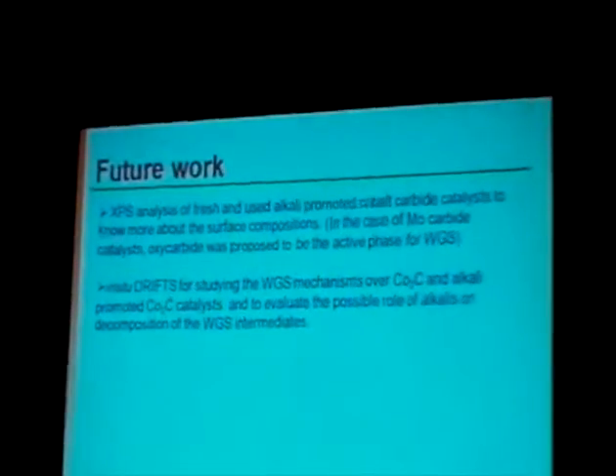And when I showed these results to Gary, he was telling me that he has seen that alkali effect, like sodium and potassium, on a platinum ceria catalyst. I guess platinum ceria, is it? Platinum. Well, first it was platinum zirconia, and Honda found that in their combinatorial work. Yeah. And so he has shown that there is a trend: sodium and potassium behaved differently than the other alkalis, and the water gas shift rate was compared with the formate decomposition. It helps decompose the formate much quicker than the other alkalis. So we are trying to see if that works on this carbide catalyst by doing in situ DRIFTS on cobalt carbide and alkali promoted cobalt carbide catalyst for the future work, in order to see what is going on at the surface.